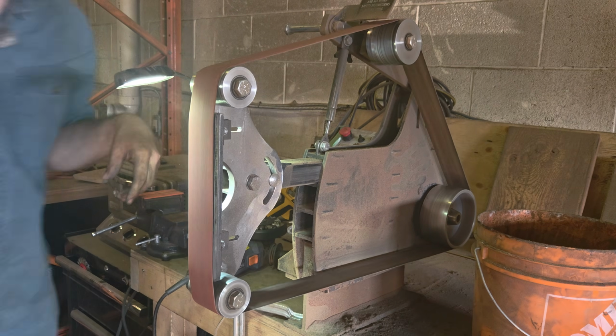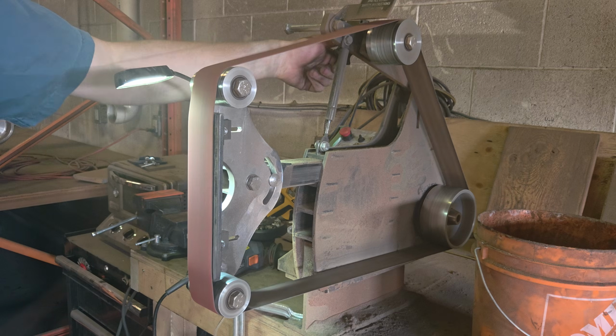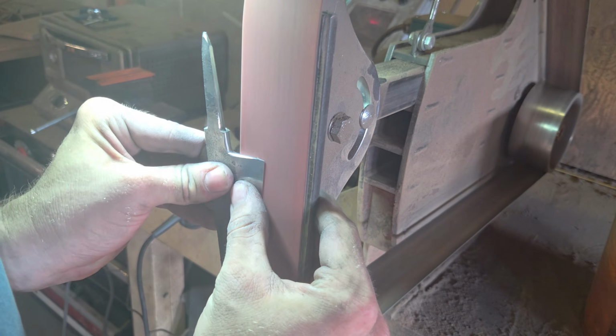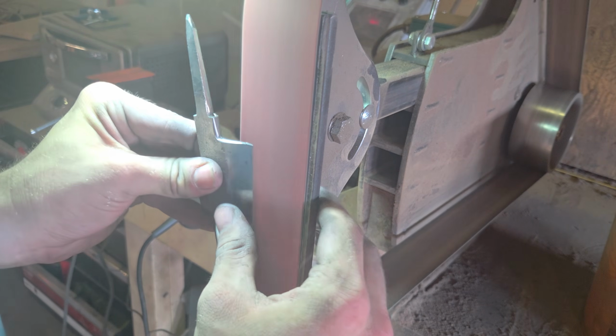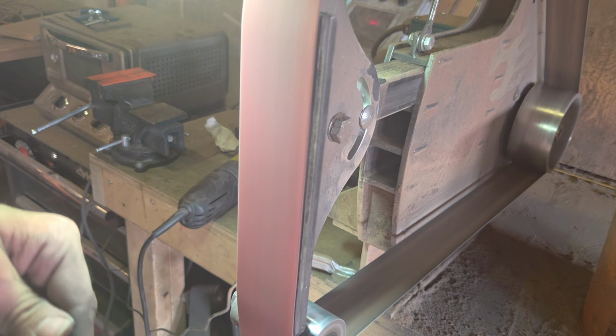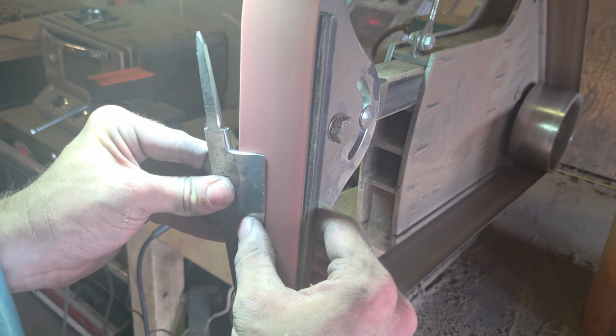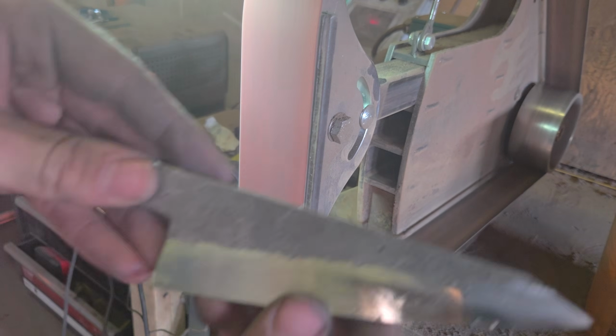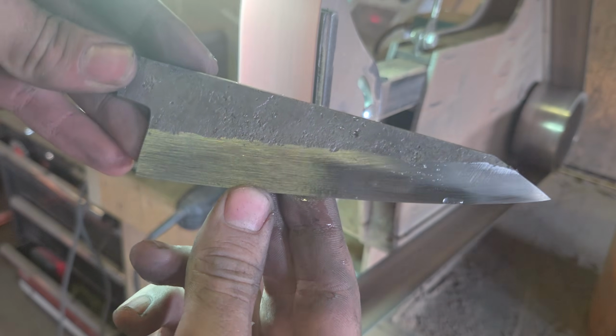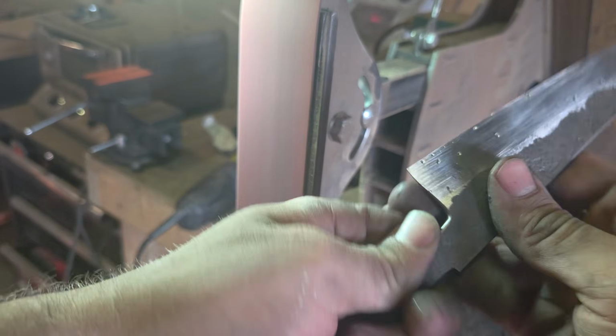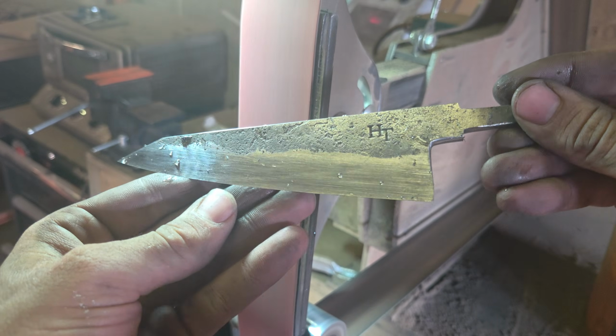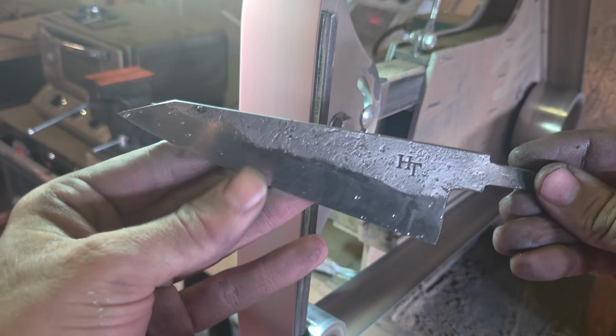After my first stage, 60 grit grinding is complete and the blade is really almost finished grinding. The geometry is completely set, the edge is very thin. I do a vertical grinding on a 120 VSM belt. This helps with my finish and helps me line everything up to keep the edge nice and straight and really precisely fine-tune that geometry and get the edge thickness where I want it.